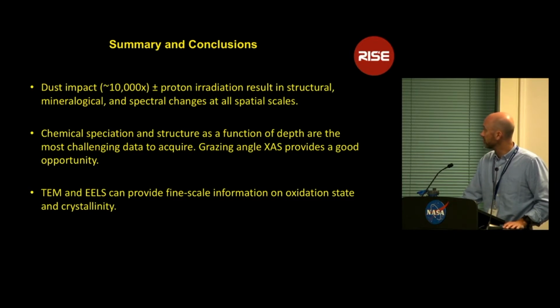The chemical speciation and structure as a function of depth are probably the most challenging data to acquire. We have our first set of beam time coming up later this fall, which we're very excited about, and probably see Sarah presenting that at LPSC, I would imagine, or AGU coming up. One thing we'll also do moving forward with our colleagues at the Naval Research Lab are TEM and EELS, electron energy loss spectroscopy, which will allow us to get information on oxidation state and crystallinity at several nanometer spatial scales.